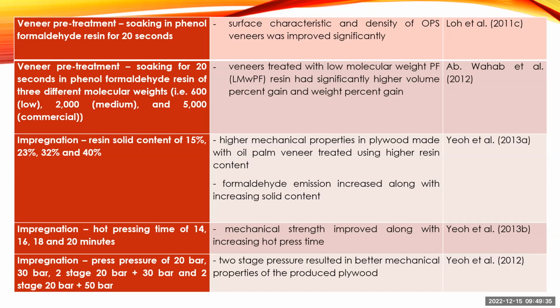The formaldehyde emission increased along with the increasing solid content. Also, impregnation was tested with different hot pressing times, and it was found that mechanical strength improved along with increasing hot pressing time.